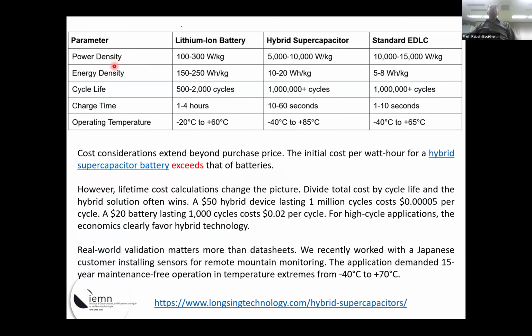Okay, so you can see here the lithium ion batteries, the standard EDLC based on carbon, and the hybrid. You see that the power density is now quite enhanced. It's almost that of the EDLC. But interesting is the energy density now. It's increased, but of course, it will never reach that of the lithium-ion batteries. The cycle life is quite enhanced. The charge time is quite reduced. You see, it's only in seconds. And now you can operate this over a large temperature window. So this is definitely something which is very interesting, and also the cost is quite reasonable according to this website. I didn't make anything.